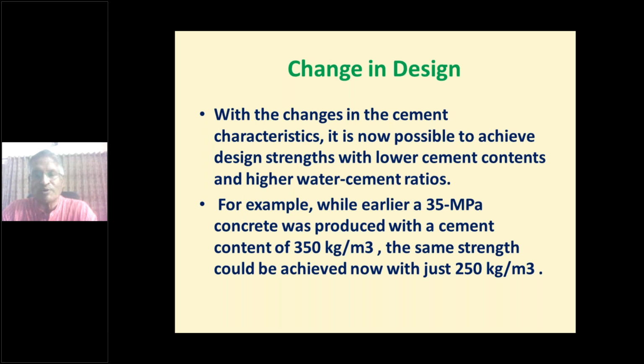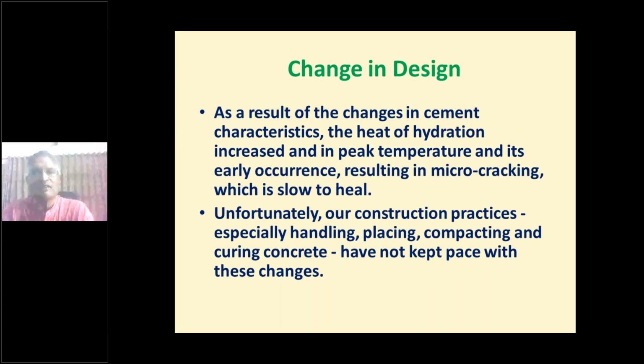Earlier, if you were able to produce a 35 grade concrete with 350 kg, today it is possible to produce it with 250 kg, with proper mix design. But then, with these changes in cement characteristics, we should also take care.